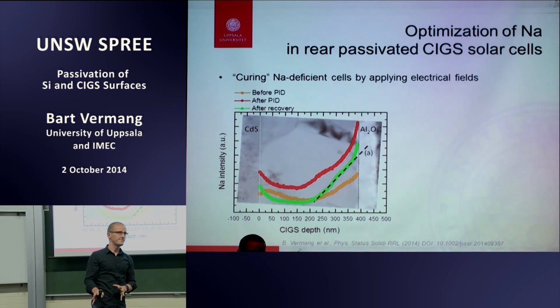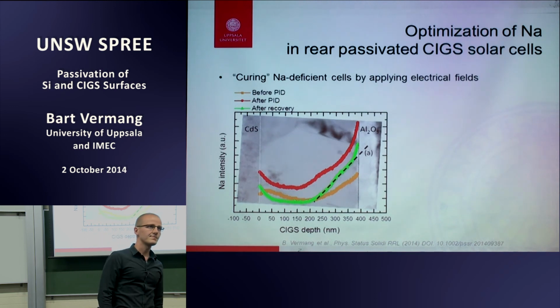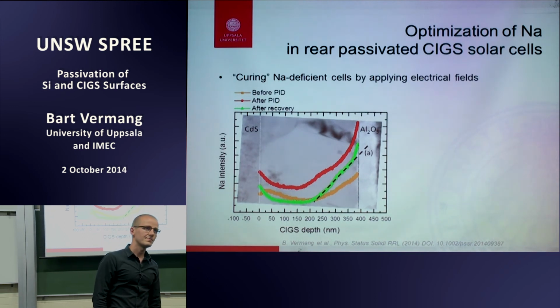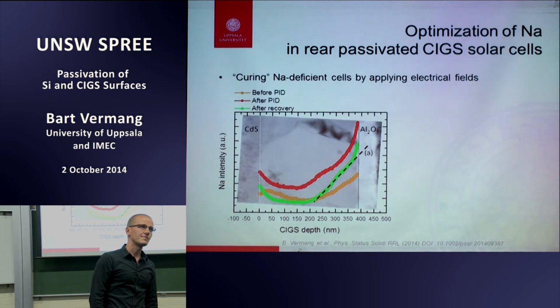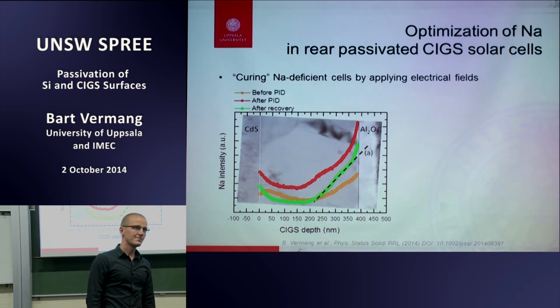This we are sure. Because with crystalline silicon, one of the theories about why the cleaning is so important before you deposit your aluminum oxide is that if you do any pre-cleaning steps with sodium and potassium, those ions stay at the surface and they get attracted. They stay at that interface because of the negative charge of the aluminum oxide, and that results in a very low Dit with crystalline silicon. So I look here and you've got quite high sodium concentrations right at that interface now.